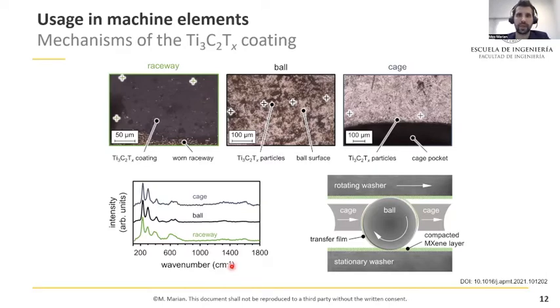So we wondered why the service life was higher than that of the reference solid lubricants. And here we can see some light macroscopic images of the raceway, the ball and the cage. On the raceway, we can see this kind of MXene layer, probably in some compacted form with partially intact, partially worn areas. But the clue is that we also found such dark spots on the balls and on the cage, although, as you remember, we only had coated the raceways. And the Raman images on the areas marked with crosses showed that there was indeed some transfer of MXene-like material. So this might not be classical Ti3C2, maybe a bit degraded form intermixed with nanocrystalline amorphous oxide structures from iron oxide from the substrate, some titanium oxide, which might be due to the mechanical shear stress, oxidation as a result also of the flash temperatures and the hot run.